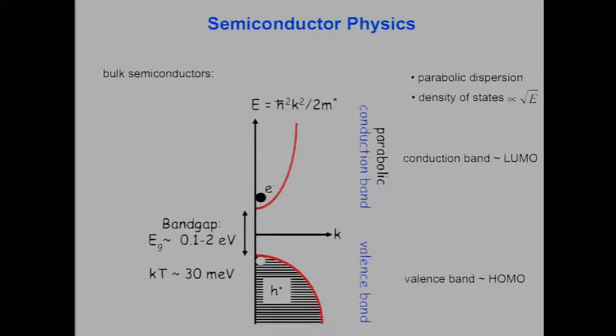Those are quasi-particles within the semiconductor. And if we have now a positive charge and a negative charge, we have something that looks very much like the hydrogen atom. Therefore, this entity is going to form something like a hydrogen atom within the semiconductor. We have electron orbiting around the hole. This is another quasi-particle called the exciton. And this exciton resides within the crystal structure.